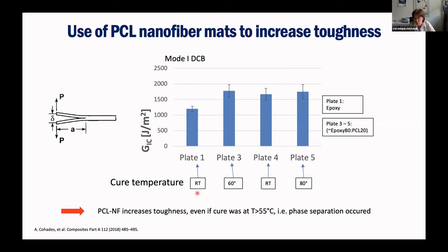And we cured it at room temperature, which was the recommended cure for this resin. Then we did several plates with the interlayer of PCL, such that we had about 20% volume fraction of PCL in the epoxy phase, in the matrix phase. And then we did either a cure at room temperature, so exactly the same as plate one. So this is just the PCL, not molten, it's cured, and we see the effect. So indeed, we have a toughening, so it works.